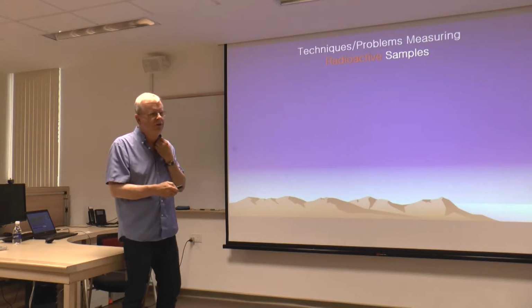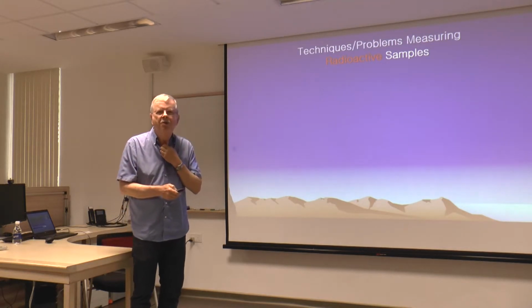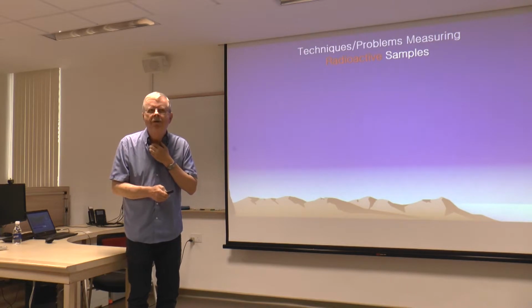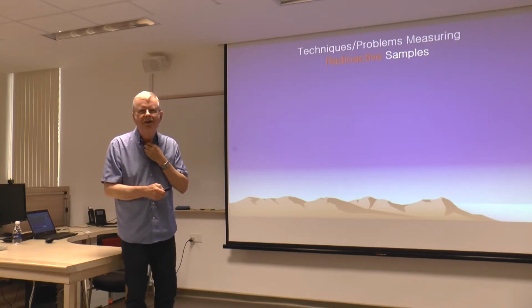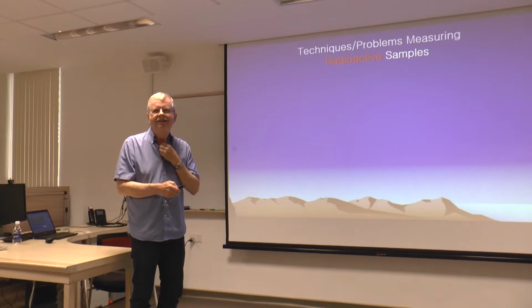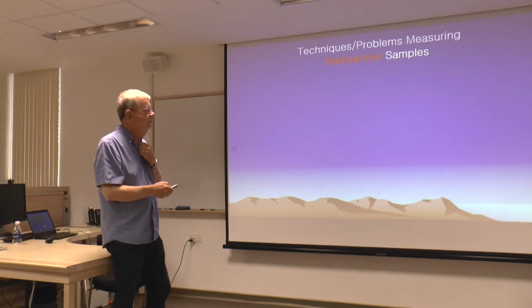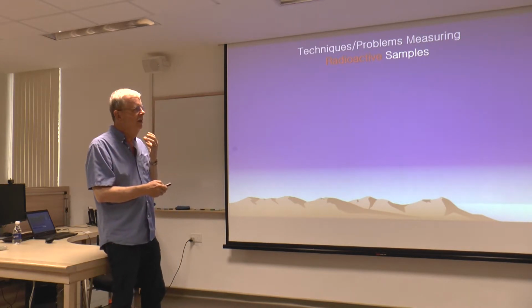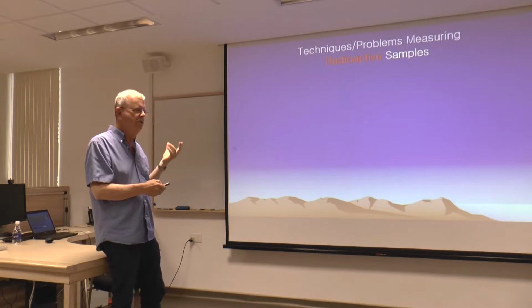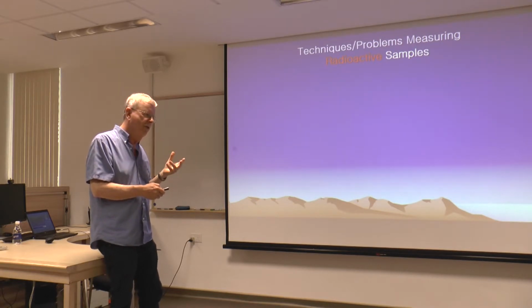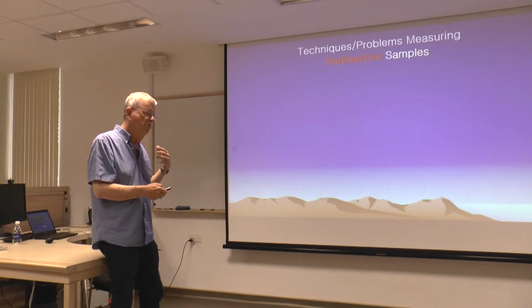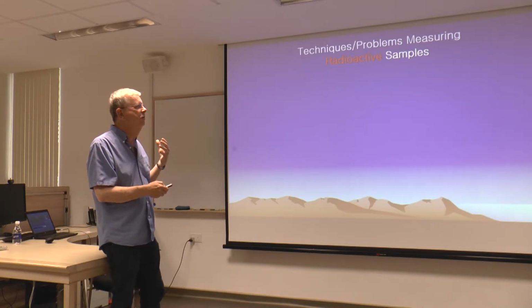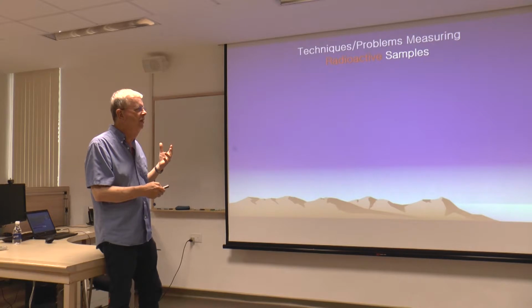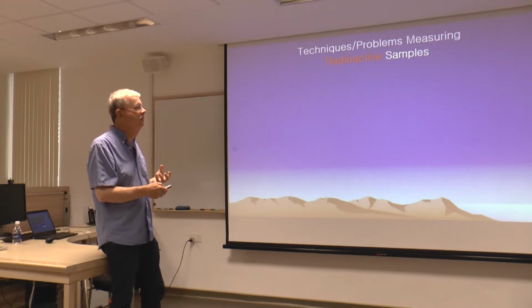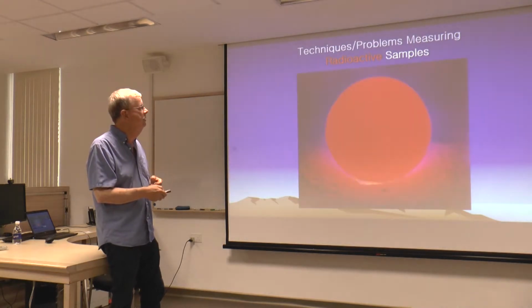So for those of you who are experimentalists, how many experimentalists do I have? Oh, what a minority. Anyway, if you're worried about how to measure these things, measuring cerium to low temperature and finding the superconductivity at 0.6 Kelvin is no problem. Measuring uranium beryllium-13 or uranium platinum-3, you have to worry about the cooling power because the uranium is radioactive and creates a self-heat.